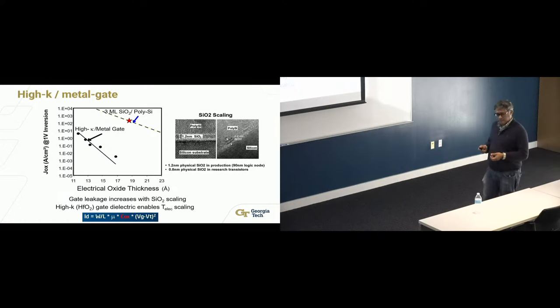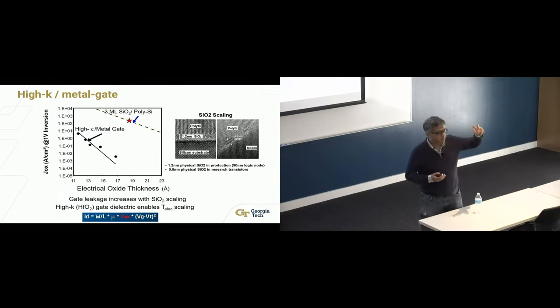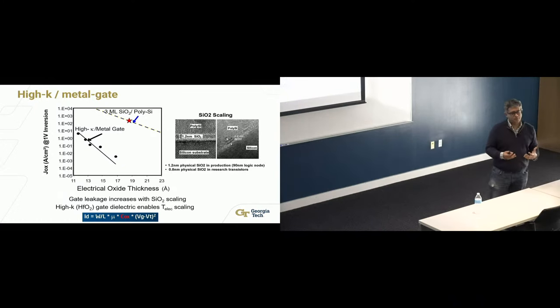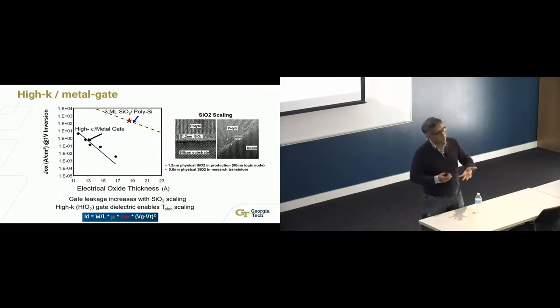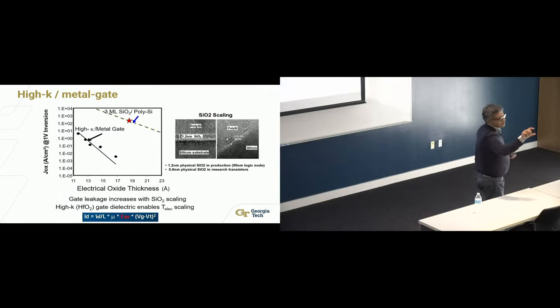The next big one that happened in our industry was related to, again, transistor scaling, but in order to scale the transistor, you have to scale the gate oxide. And we were at a point in our gate oxide, back in 2000 or early 2000s, where the thickness of silicon dioxide was already approaching about three monolayers, no more than 12 angstrom. If you try to go below 12 angstrom, typically you get a lot of quantum mechanical leakage. Basically, it's direct tunneling: the channel electrons will tunnel right through that gate oxide, reach the gate electrode, so you get a lot of gate leakage current.